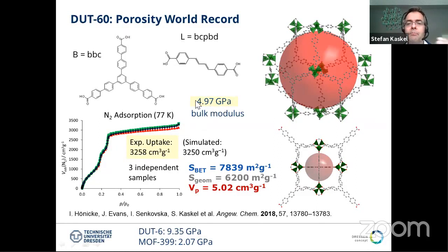And basically, here we are approaching the bulk modulus of a fluid. So you can imagine that this spider net becomes softer and softer. And this is actually the challenge in these types of materials, to balance mechanical stability and ultra-high porosity. Just to give an example, MOF-399, which is a structure developed by Omar Yaghi, has only a calculated bulk modulus of 2 gigapascal, and it was never reported as a porous material. So there might be a limit between 2 and 5 gigapascal to reach these high specific surface areas.